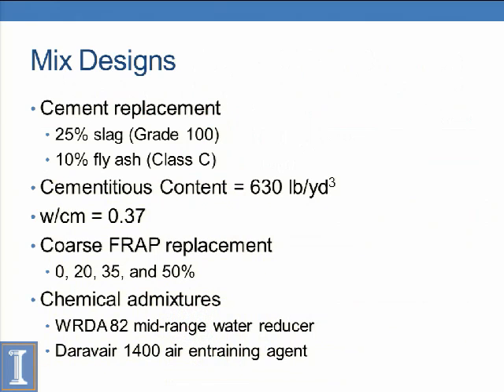Mix design. So like I said, this was a ternary mixed concrete, which consisted of 65% cement, your normal Portland cement. Then there was 25% ground granulated blast furnace slag. That's just a byproduct of steel production that's used commonly in concrete. Another thing was it was 10% fly ash, which is from coal burning. And both of those products are commonly used in concrete. Usually you only replace with one of those.